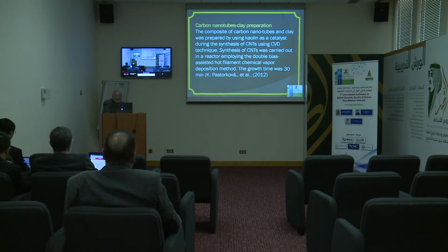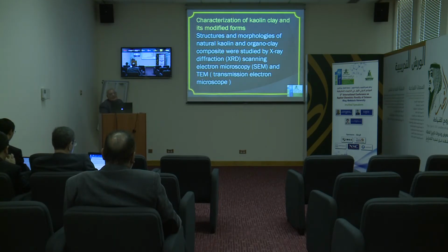Carbon nanotubes clay preparation, as we referred before, has been prepared here. The clay, kaolin, was used as a catalyst during the synthesis of carbon nanotubes using the chemical vapor deposition technique. Synthesis of carbon nanotubes was carried out in reactor employing the double bias assisted hot filament chemical vapor deposition method. The process time was 30 minutes.